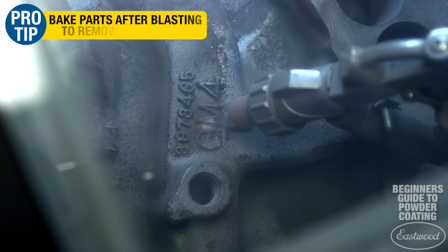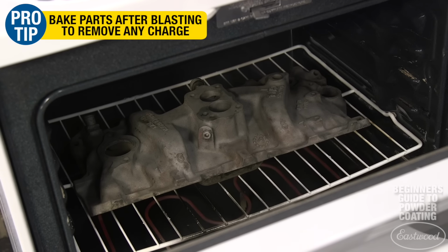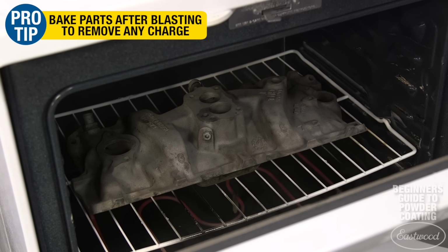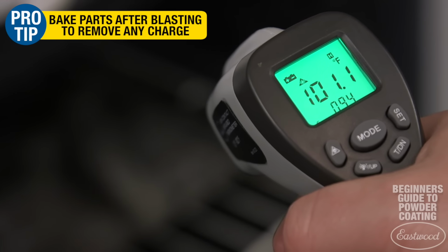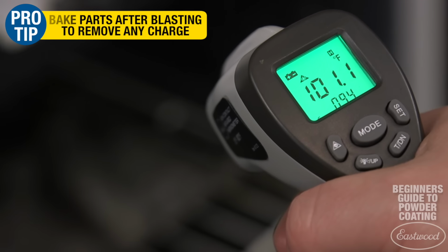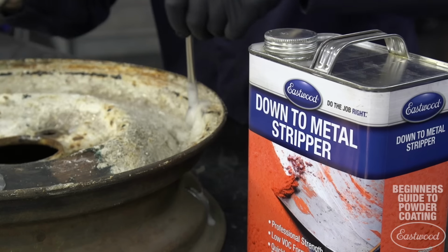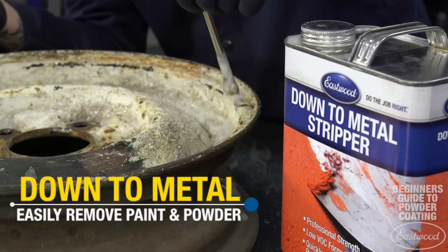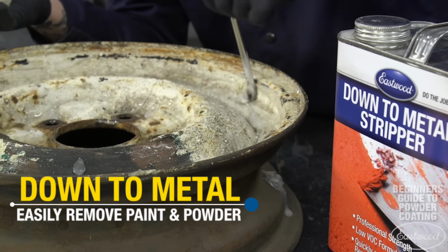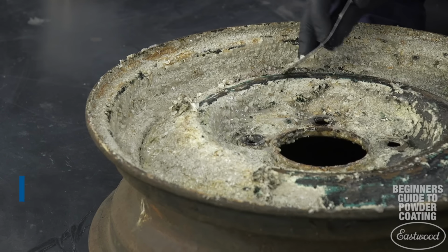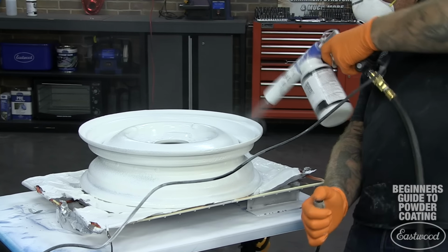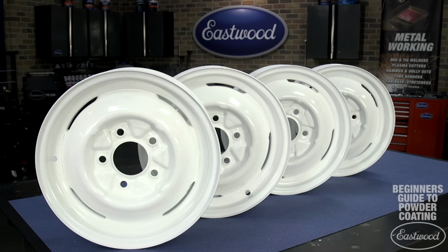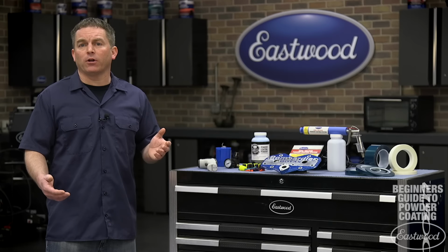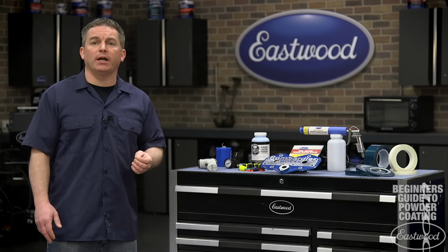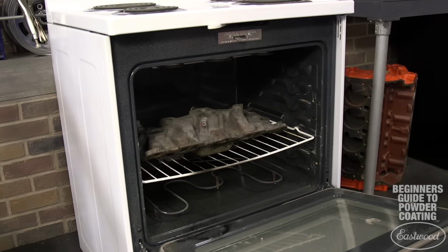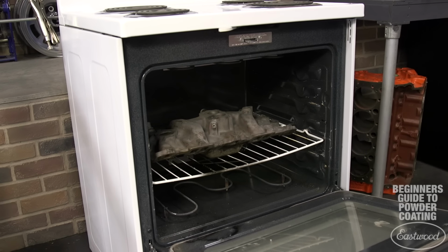If cleaning a part by blasting, it's a good idea to place the part in the oven and heat it until it reaches 100 degrees. This will remove a charge you may have created while blasting that could affect your coverage. You can also use a chemical stripper like Eastwood Down to Metal to remove these coatings, which we've done with other projects, like when we restored an old set of wheels and covered them in Eastwood Gloss White and Cosmic Clear. If you're powder coating a cast part, it's also a good idea to place the parts in a 450-degree oven for an hour to bake out the impurities.